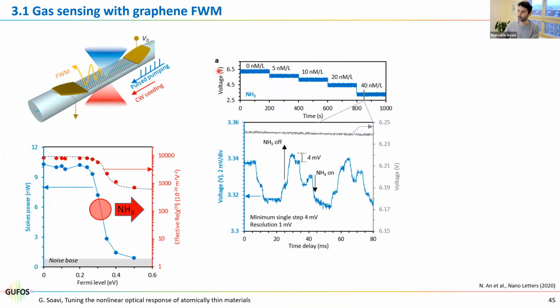What we do now is we look at the voltage, but the voltage is just a detection. So it's the voltage on our detector. So basically it's the number of photons again. And every 200 seconds, we change the concentration of ammonia in our chamber. And you see that we start from no ammonia at all in the chamber. Then we increase the amount and we have a reduction of the four-wave mixing efficiency. And every time we increase the amount, we have a further reduction of the four-wave mixing efficiency.